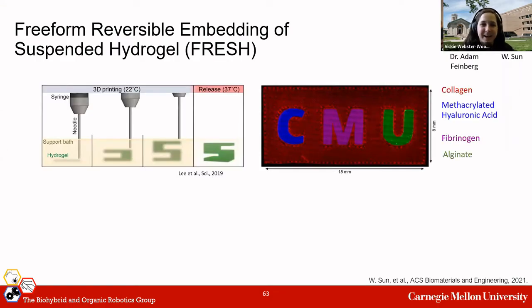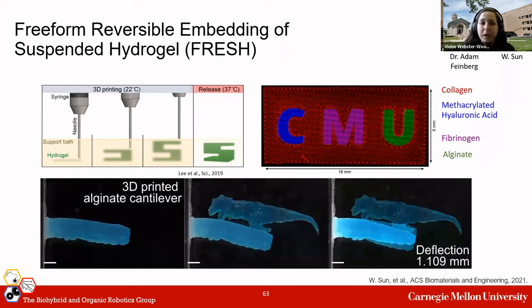This is a technique that his group developed to allow soft hydrogel and biomaterials to be printed into a support bath so that you can print overhangs and very small features that would not otherwise be achievable. The process is compatible with a number of different bioinks and hydrogels that are of interest to the tissue engineering community. And so this is a really great fabrication platform for these types of approaches. However, the resulting printed structures and materials are still very soft and fragile, right? Just like 3D muscle culture.